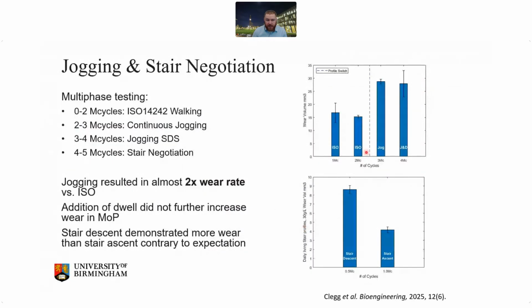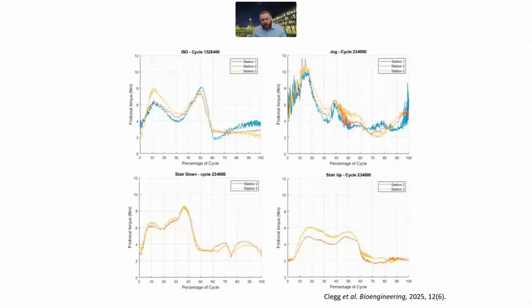We also looked at stair descent and stair ascent for only 500,000 cycles each, but the takeaway message there is that stair ascent is typically considered to be more of a severe profile, just because of the deep flexion and leverage that's involved in climbing stairs. But actually, we found that the stair descent was more important, and that's likely because one of the other advantages of the simulators is they're all instrumented with 6-axis load cells, so we can resolve the torques at the bearing surface, and the stair down had a much higher peak in resultant torque compared to the stair up.